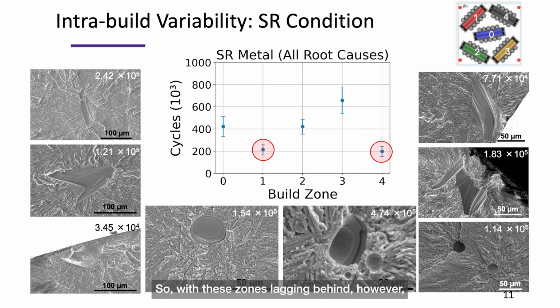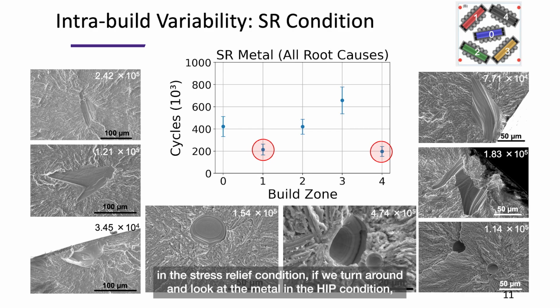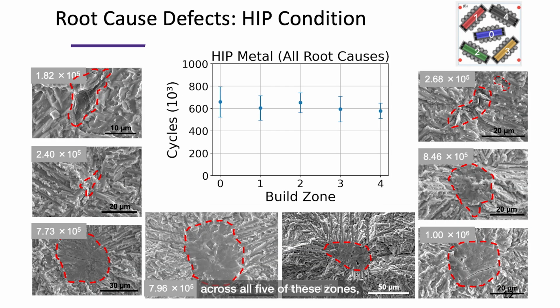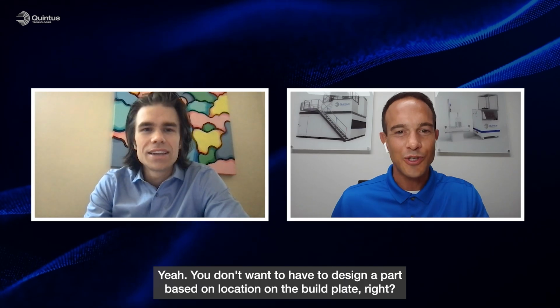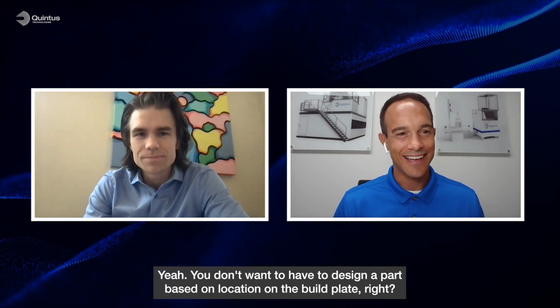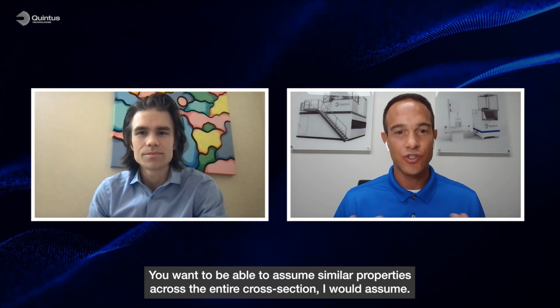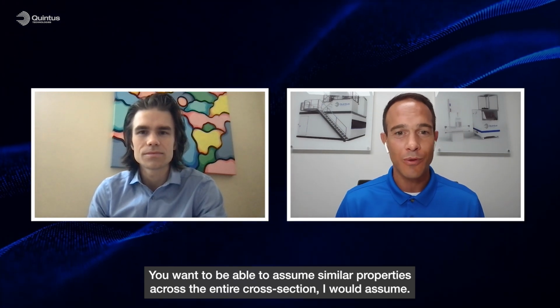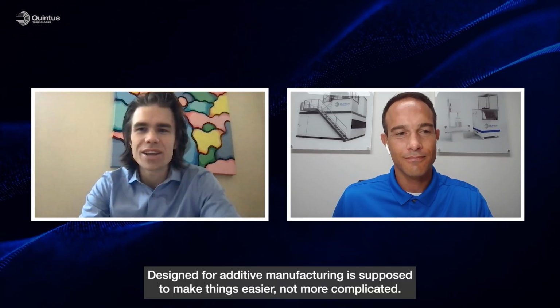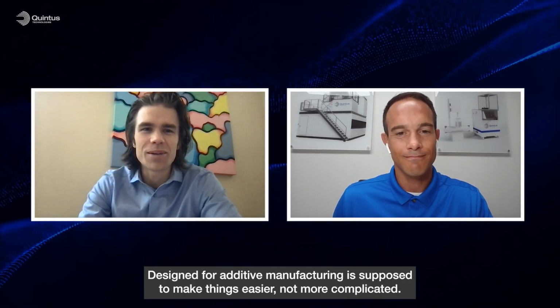So with these zones lagging behind, however, in the stress relief condition, if we turn around and look at the metal in the HIP condition, we can see very good agreement across all 5 of these zones, which effectively means the HIP process is reducing our differences, not only between specimen orientations, but between the printing regions, the location that it's printed in on the build plate, which is great to see. Yeah, you don't want to have to design a part based on location on the build plate, right? You want to be able to assume similar properties across the entire cross section, I would assume. Yeah, exactly. Design for additive manufacturing is supposed to make things easier, not more complicated, I think.